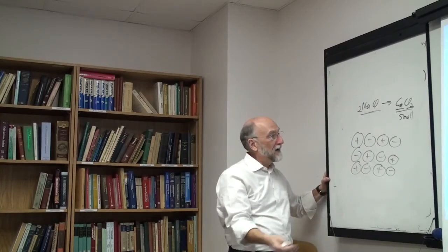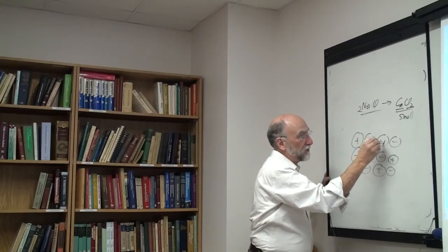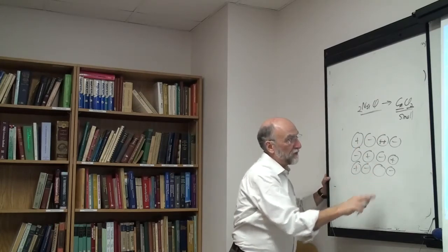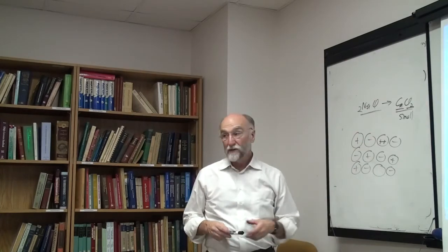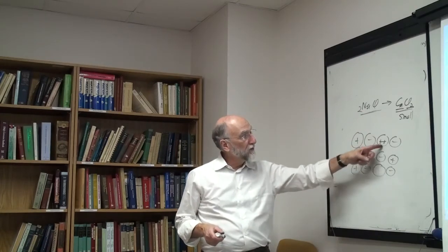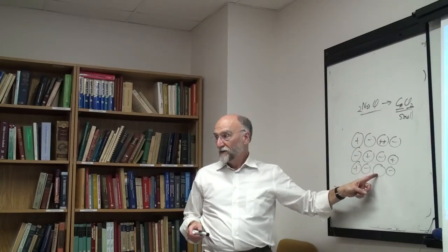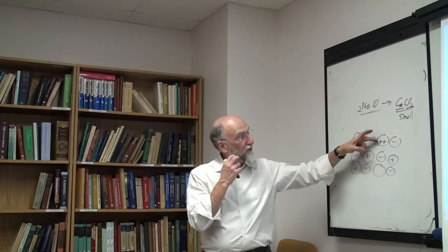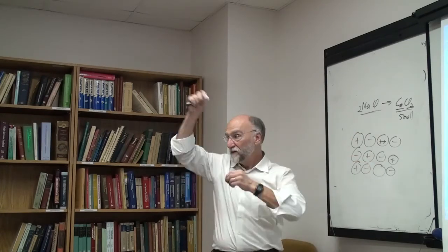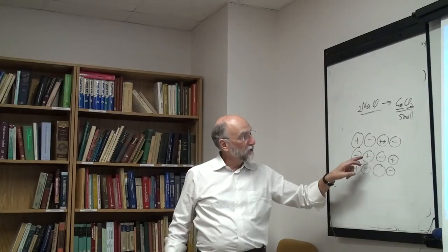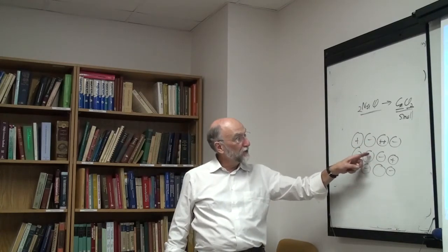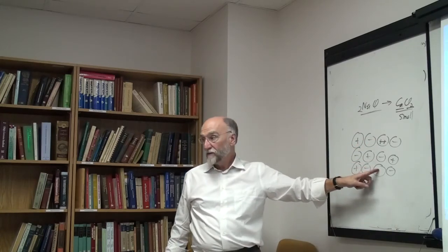The only way to do that in a solid is for the calcium to replace 2 sodiums and for there to be a vacancy. You remove 2 sodiums, replace them by a calcium. The chlorines stay the same. Okay, but now you've introduced 2 particles. You've introduced a calcium and a vacancy. So you've introduced twice the entropy. If this calcium and vacancy can move apart, can go wandering off by themselves, they're randomly distributed. Okay, so over the cation sites you're distributing sodiums, calciums, and vacant cation sites.